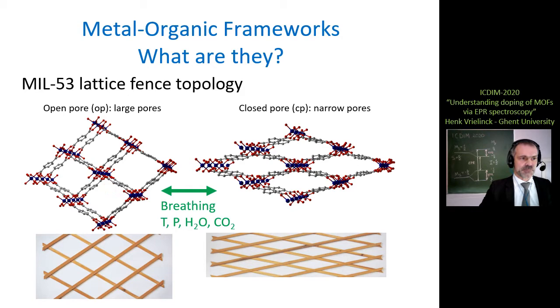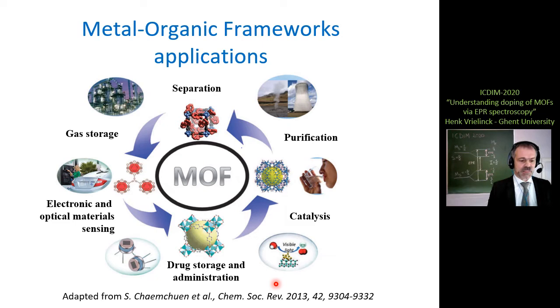Most MOFs are insulating materials. They are considered as electronic and optical materials and used in sensing, but the bulk of applications so far lie in gas storage, separation, purification, and heterogeneous catalysis. Defects like missing metal nodes, missing linkers, and various types of substitutional impurities on the metal and on the linker sites are believed to play a key role in many of these applications. Engineering defects has become an important aspect of current MOF design. Our interest from the very start has been in metal doping of metal organic frameworks.